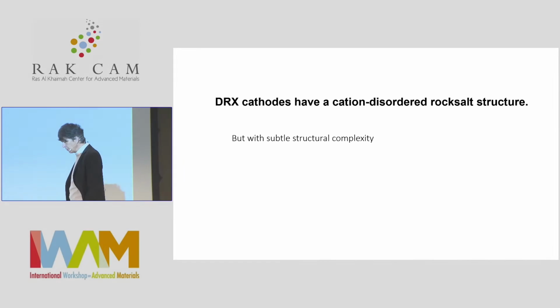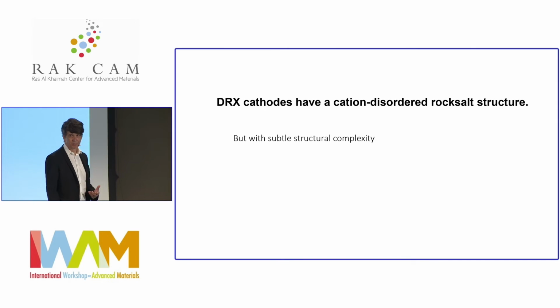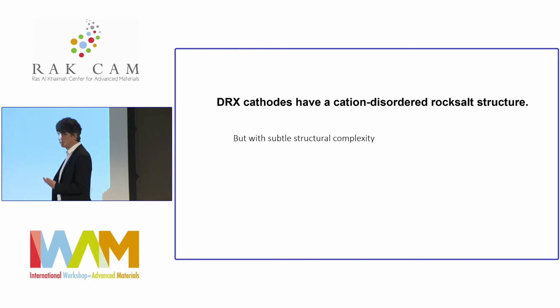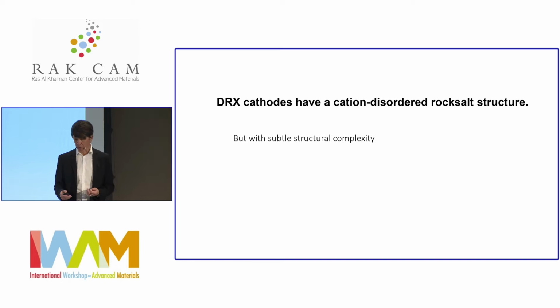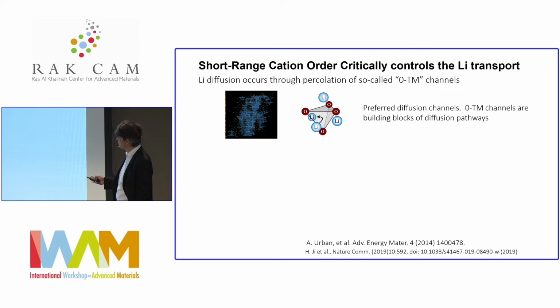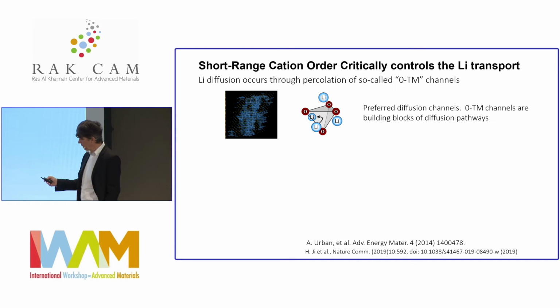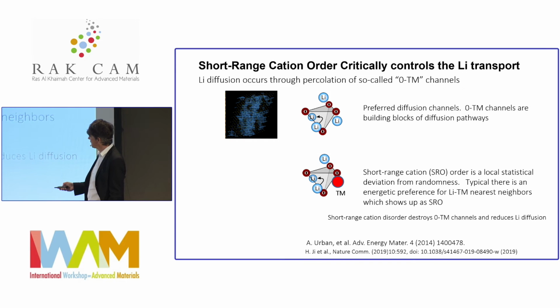Okay, so these materials look boring structurally at first in X-ray diffraction. But what we found, and others have found, is that there's really a subtle structural complexity which turns out to be remarkably important for performance, and it has to do with short-range cation order. So remember that for transport, you really want to build a lot of these, what are now called 0TM channels, right? These tetrahedral configurations of lithium are the key to lithium transport. But if you think about it, this is probably not a preferred environment because you have four 1+ cations. So what actually happens, even when they are statistically disordered, is that you tend to build short-range order where the transition metal wants to be nearest neighbor to the lithium. And the short-range cation order is actually destructive to transport because it destroys these 0TM channels.